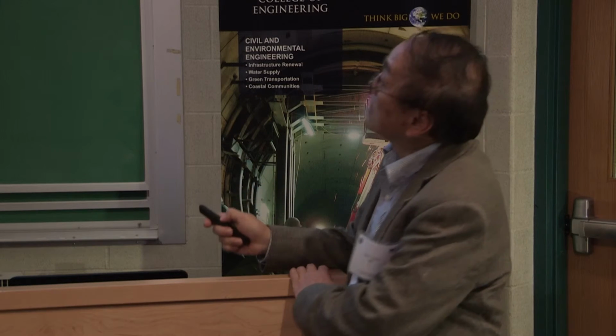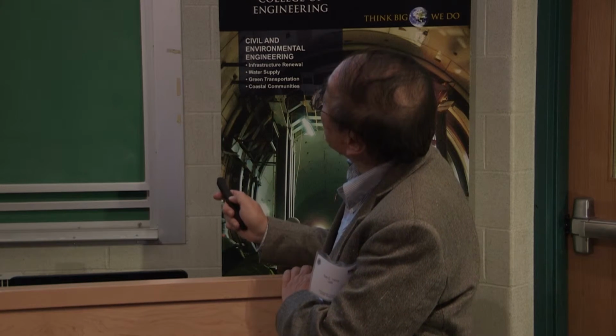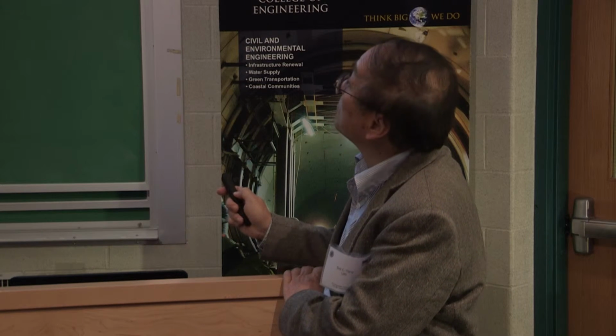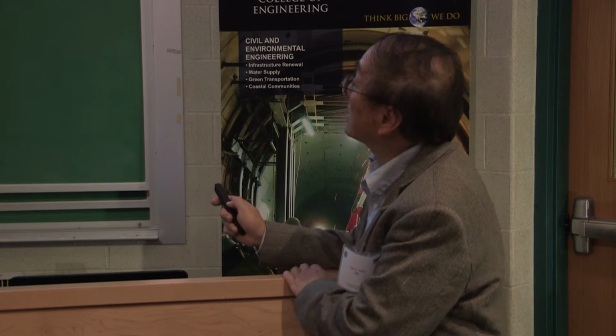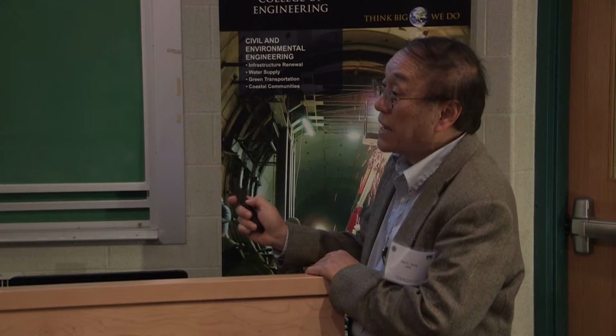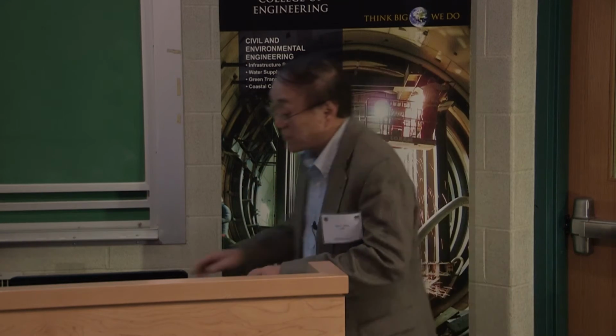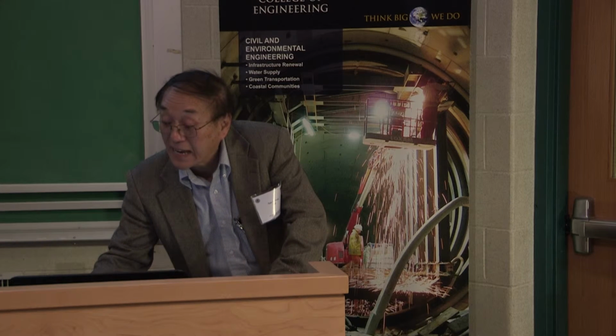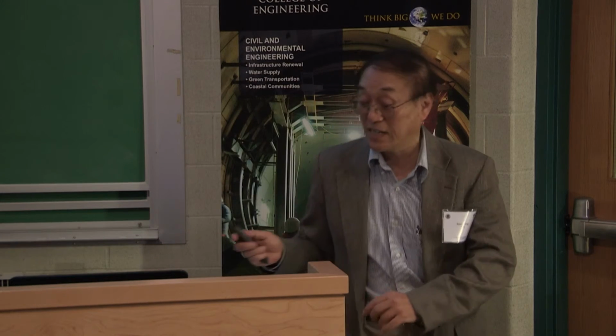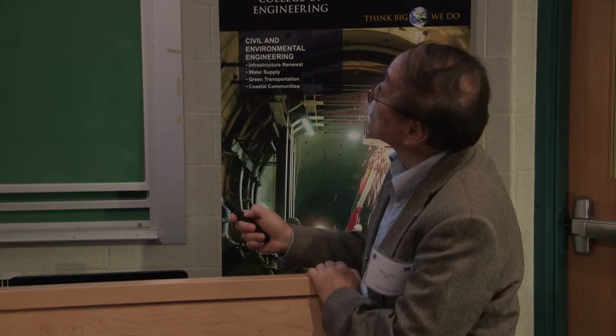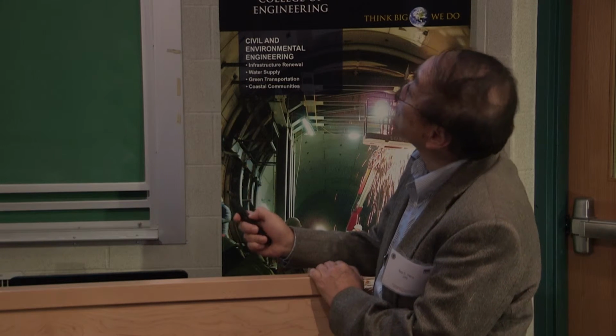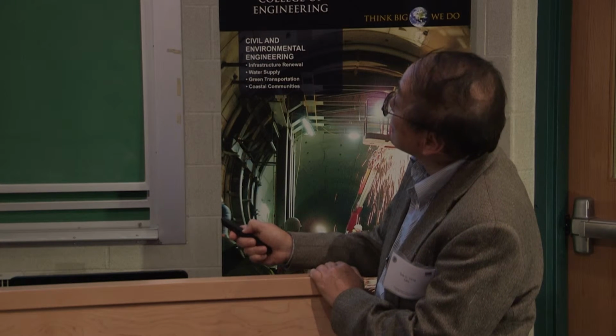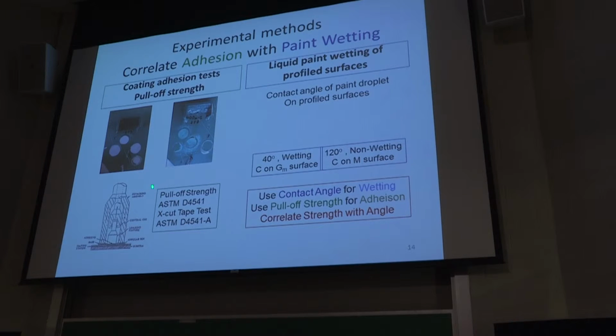And now, for different paints, before we paint it, we have this roughened zinc surface, and we put drops of the freshly prepared, formulated liquid paint on the surface and measure its surface tension as a function of time, and that is a measure of the wetting process. So now this is the standard pull-off strength test: basically this knob glued on the surface, and then there's a hydraulic pulling, and we measure how many pounds per square inch it pulls off.